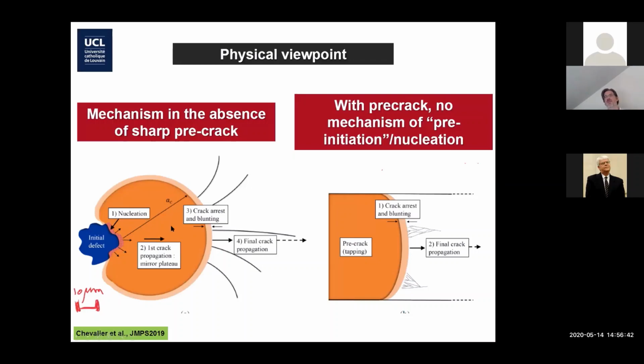If you start with a smooth specimen or a notch specimen, anything with no real pre-crack, there are always some tiny defects in the material. There is a nucleation process, something around the defect. There is this fast crack, which stops. There is a crack arrest. And then there is a reloading phase, a little bit of plasticity, and then crack propagation. This is what we observe, and now we have looked at other thermosets, and we do see the same.